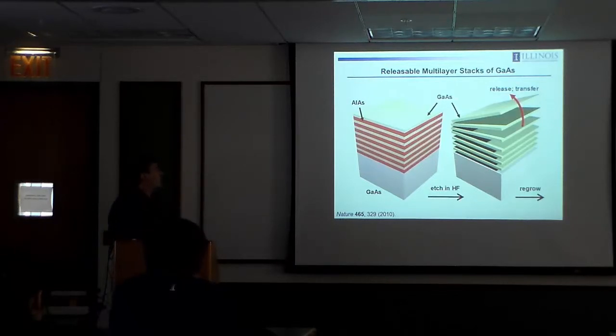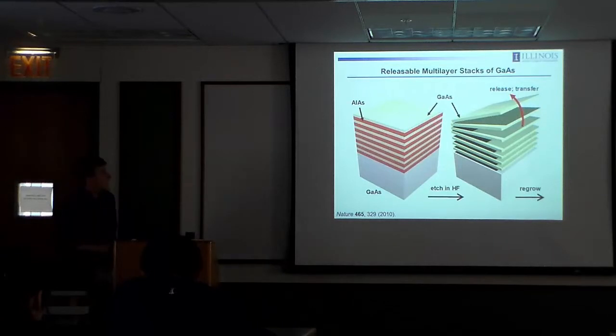So for example, you can create these membranes in this kind of strategy. You do MOCVD growth of gallium arsenide and aluminum arsenide in alternating layers. And that's interesting because when you etch down through this stack, you immerse it in HF, you will selectively eliminate the aluminum arsenide, lifting off the surface of the growth wafer bulk quantities, essentially these gallium arsenide nano membranes. And then you can reuse the wafer. So this provides a really easy and powerful route to extremely high quality, very thin sheets of semiconductor materials.